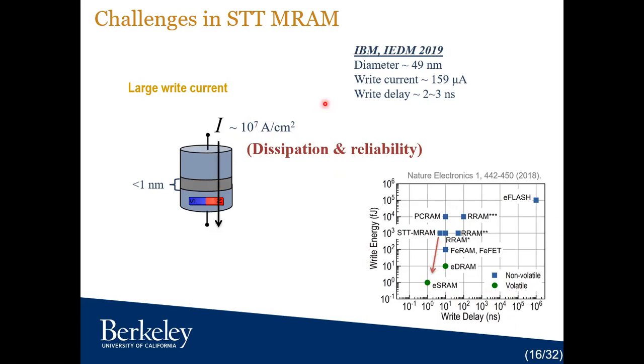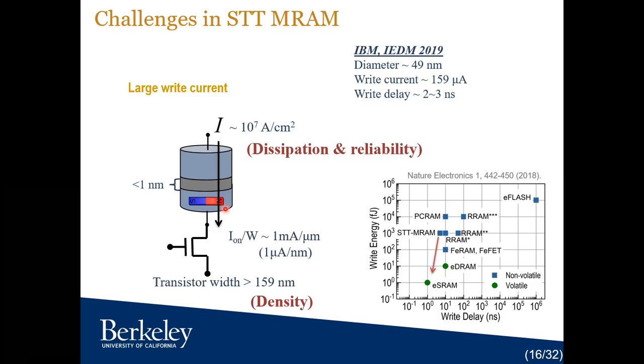Another problem associated with this large write current is that we're running the current through this device, but in a large array, we need to select a particular bit. So we need a transistor, and the same current will flow through this transistor. The best transistor can give you an on current per unit width of about 1 milliamp per micrometer, which is the same as 1 microamp per nanometer. So you can see, to accommodate this write current, your transistor width has to be at least 159 nanometer, right? Because your write current is 159 microampere.